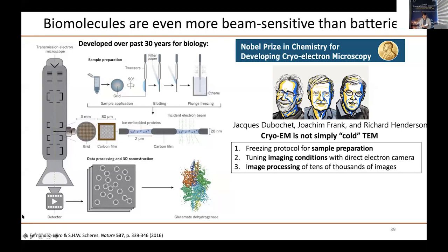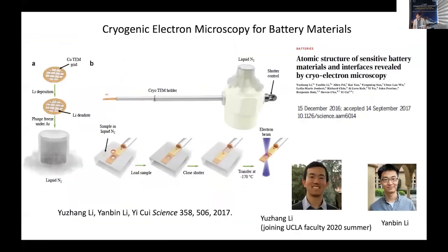Very impressive. So we were the first group to adopt this technique, starting to work on it in 2016, and published the first paper in 2017 in the battery field. My 2 graduate students, Yanbin and Yuzhang, took on this challenge. Yuzhang just joined the UCLA faculty after graduating from my lab. They developed the cryo transfer technique: we deposit the lithium dendrite onto the TEM grid, then plunge-freeze it into liquid nitrogen, freezing it very fast, and develop a cryo transfer without exposing it to the air. That's very important. Make sure you don't expose it to the air. Transfer it into the TEM. This TEM holder is a cryo holder. We have liquid nitrogen through this cold finger, maintaining the sample close to liquid nitrogen temperature.